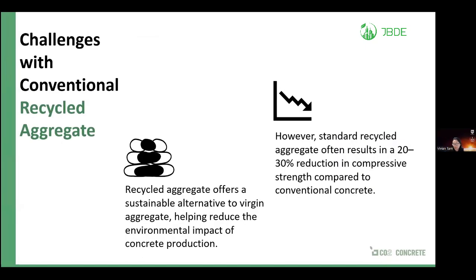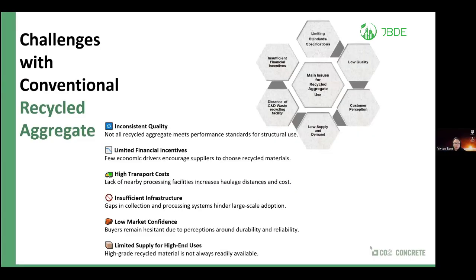And that also gives hesitation in the industry to use this particular product, because there are no standards allowing it. And bringing it into the challenge, I think you can very clearly see that recycled aggregate is an alternative to virgin material, and it is needed to reduce the environmental impacts of concrete production. However, because the performance is relatively lower compared to virgin aggregate, normally about a 20 to 30% reduction in strength, it is also limited to different applications compared to what concrete is supposed to be able to be used for.